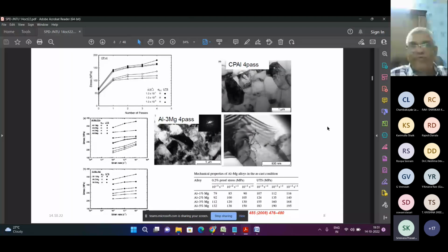This work we have done for pure aluminum with 4 pass samples, and we have shown the TEM image also. I think by using that micron bar, 15 is 1 micron. So the grain size is less than 1 micron. You can see that there is no grain having more than 1 micron. Whether you measure length, width or height, this is less than 1 micron. That's how you can generate ultrafine grains of 0.9 microns, or 0.95 microns, in the case of commercial pure aluminum.